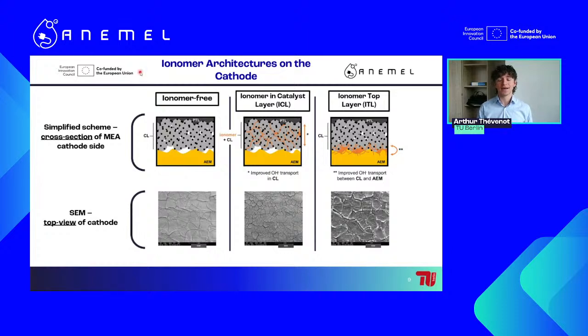So the idea then, as we are scarcer in OH- ion content, was to use an ionomer in order to improve the transport of these OH- ions. And our hypothesis is that it's actually important to do it on the cathode side. This is a critical side, to do it on the cathode specifically, and not just on the anode, as we already have some ionomer on our anode side. And we also see in the literature that they explore a lot on the anode side. Only a few had some trials on the cathode side. And therefore, what we wanted to do through this study was to thoroughly study the impact of different ionomer architectures on this cathode catalyst layer.